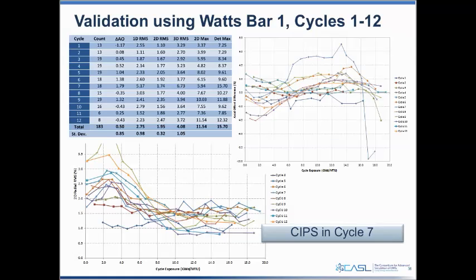And we can bring all of that together and look at cycle by cycle comparisons. In the top left, there's a table with cycles 1 to 12, showing how many different detector counts were recorded, the change in axial offset between measurement and experiment, the 1D axially integrated core average root mean squared error, the 2D assembly average root mean square, and the individual 3D maximums and other areas to see how these various cycles were performing.